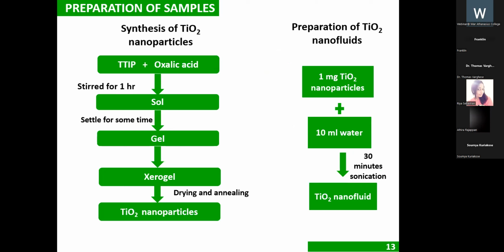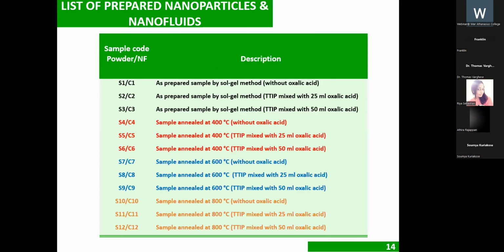In order to prepare the TiO2 nanoparticles, a sol-gel method was used with TTIP as the precursor, and different concentrations of oxalic acid were also incorporated into the precursor to prepare the TiO2 samples. To prepare the nanofluid for the Z-scan study, I mixed 1 mg of nanoparticles in 10 ml water, which was ultrasonicated for 30 minutes.